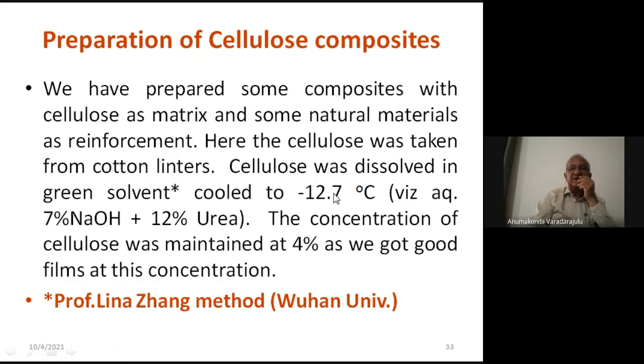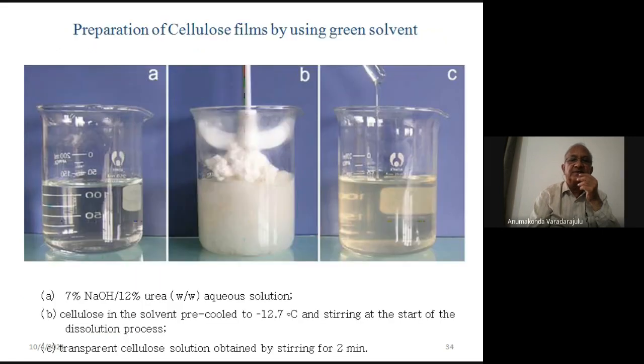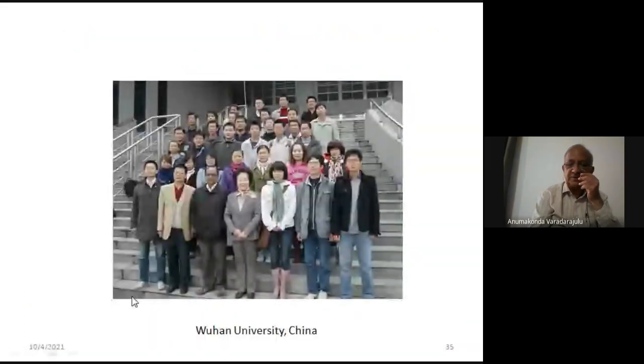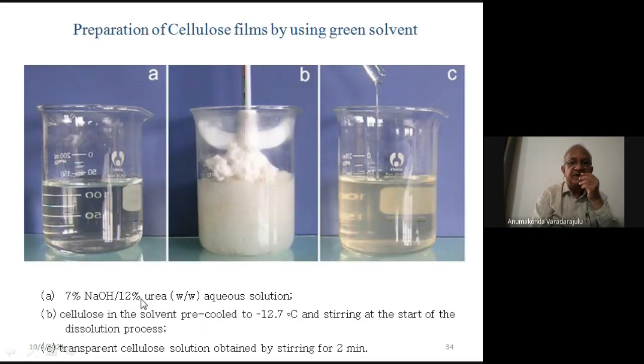And that was used as the solvent for the cotton. We used 4% of the cotton linter, and I will show you the procedure here. So this is a pre-cooled solvent at minus 12.7, 7% sodium hydroxide and 12% urea. After cooling, you can keep it outside and then add the cotton linter to this solvent and stir it. You require a magnetic stirrer. It is available in most of the laboratories. Within 2 minutes, you will be getting a solution. Let me show this clipping.